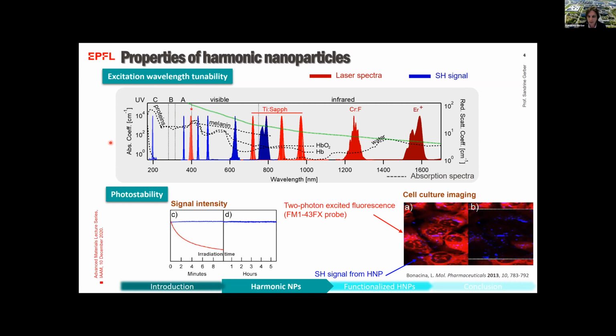Also, in addition, they benefit from long-term photostability in comparison with fluorescent labels, as shown here in this cell culture, which has been incubated with harmonic nanoparticles. You can see that the emission of the nanoparticles is highly stable over time, even after several hours of excitation, while the signal from the fluorescent dye is vanishing after a few minutes of excitation. So these are two advantages of those nanomaterials.